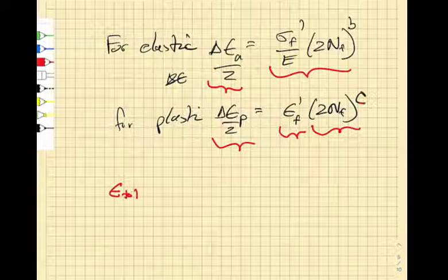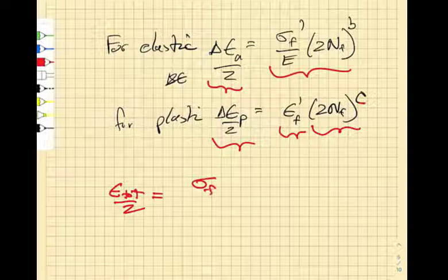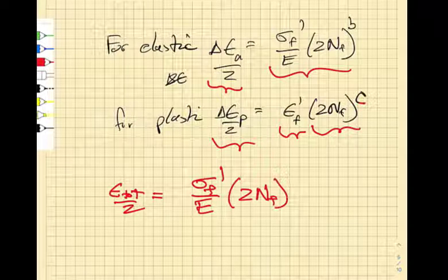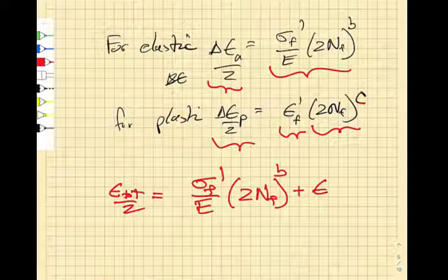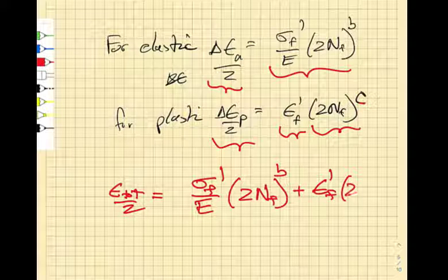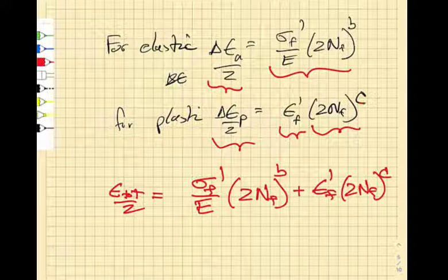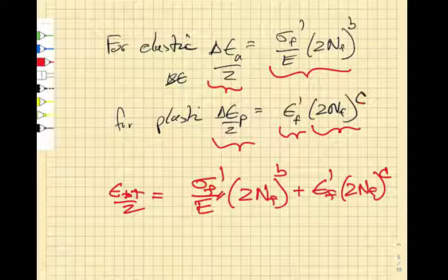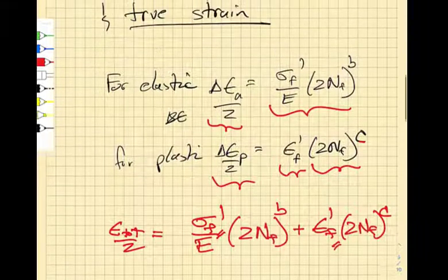the total strain amplitude, is going to be equal to the elastic strain amplitude times 2Nf to the b plus this plastic term times 2Nf to the c. And these are true stress and true strain. I'll get to that in a moment.